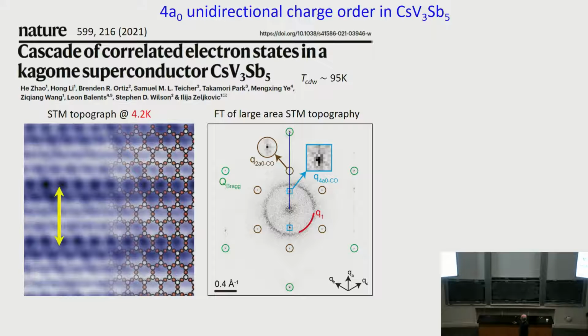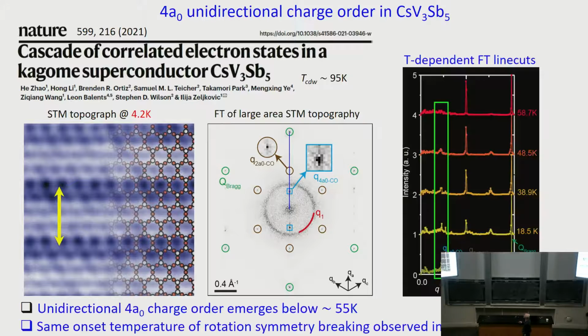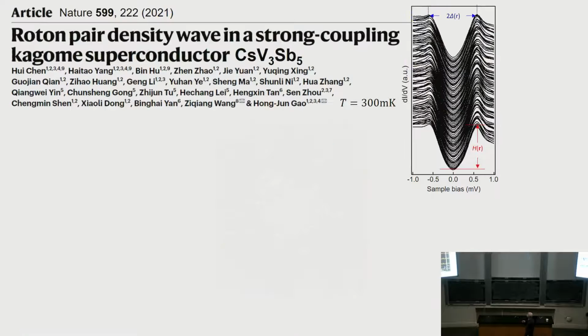And these 6 are the CDW peaks, right? And there are 2 more additional ones along one direction at the quarter G. And these are 4a0 ordering, right? They arise around 55 Kelvin-ish. And that breaks rotation symmetry. You can observe those in transport.